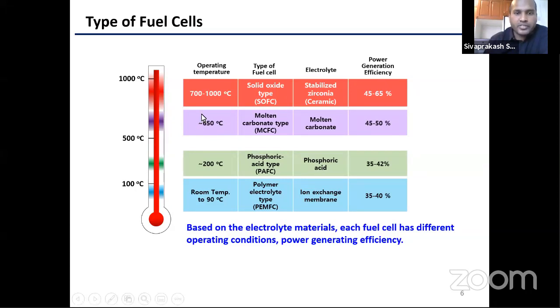The second type of fuel cell is the molten carbonate fuel cell, which operates at about 650 degrees Celsius. The electrolyte is molten carbonate, and the efficiency is only about 45 to 50%.